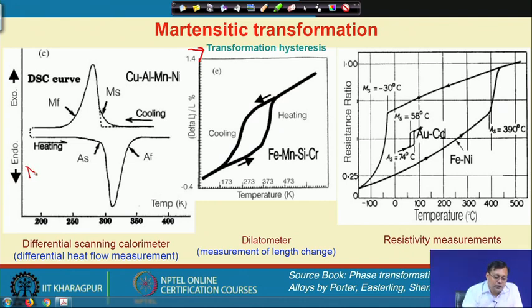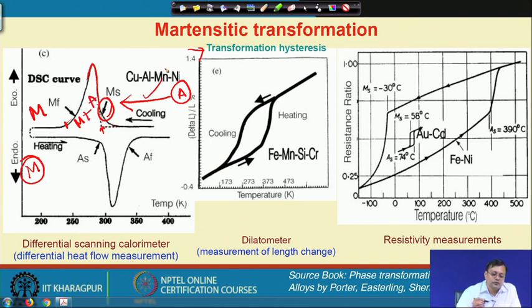So, if we start with a martensite from room temperature, or maybe we can start from an austenite from a higher temperature, this austenite could be cooled and then martensite will appear here. This is the onset of the transformation, which can be estimated through the tangents, and then the transformation continues, and here is the end of the transformation. So, here all the phase is martensite, here martensite plus austenite, and here it is austenite.